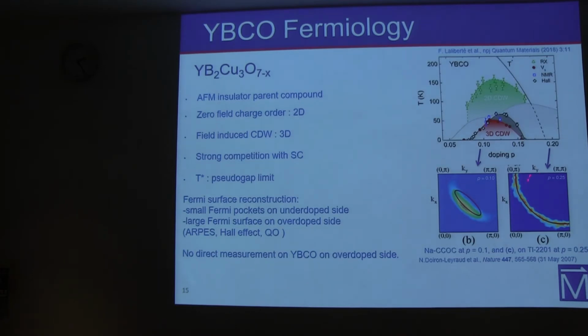So all of those measurements were actually done on analogous samples. Basically the thallium doped cuprate, depending on the amount of charge carriers that are in the copper oxygen plane, people decided that it was a good analog to the overdoped YBCO. So this picture actually comes from a completely different sample. Currently there are no direct measurements on the Fermi surface of YBCO on the overdoped side.